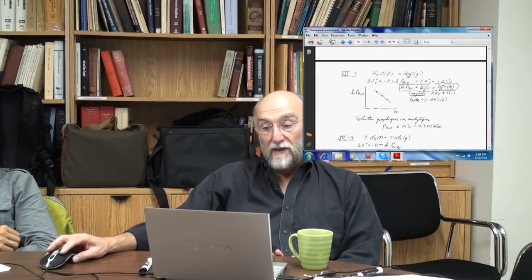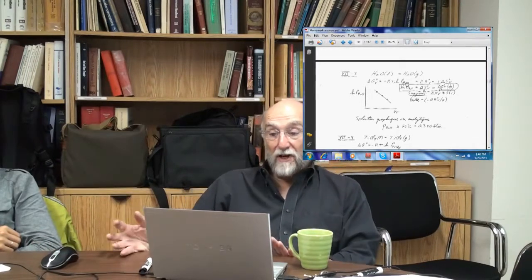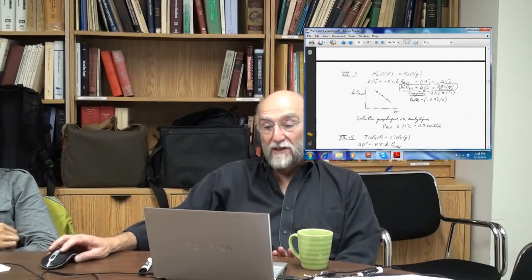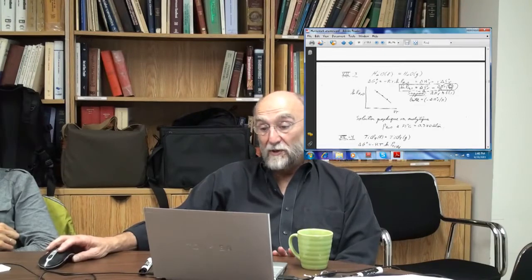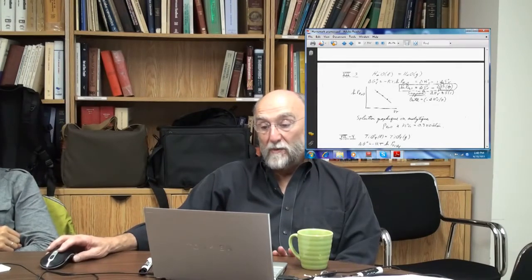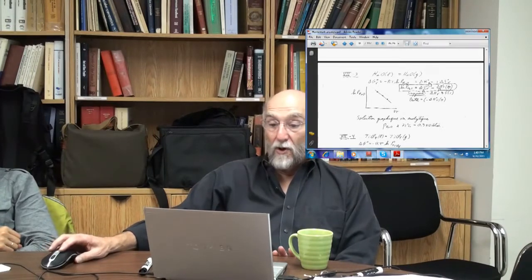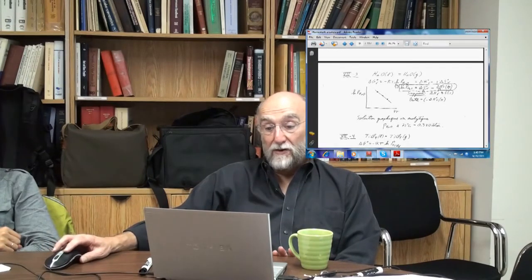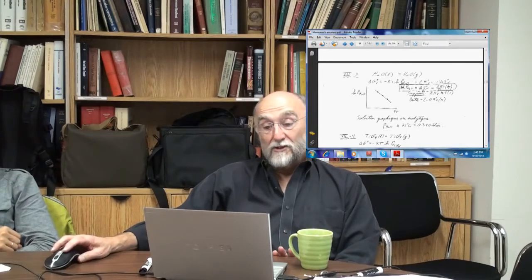So the partial pressure of the gas at equilibrium, which is the vapor pressure by definition, gives delta G0 equal to delta H minus T delta S. So if I plot RT log of vapor pressure versus temperature, the slope would be minus delta S, the intercept would be delta H, like in the last question. Or I can do it differently. I divide through by RT. I'm just dividing through by it.